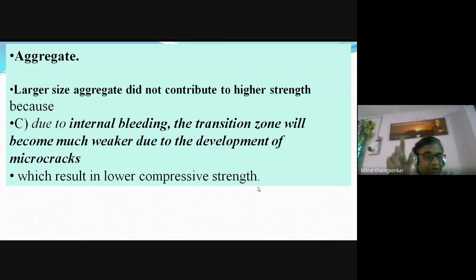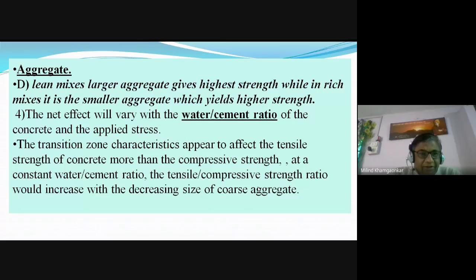Okay, sometimes it is asked in exams why the larger size aggregate gives lesser strength as compared to the smaller size aggregate, or whether the concrete of larger MSA is stronger than the concrete of smaller MSA. You should be able to answer that larger size aggregate does not give higher strength as compared to smaller size aggregate because of these three reasons. Okay, and the last but not the least, which adds to the strength of the concrete due to the larger aggregate, is the lean mixes, means the concrete with lower cement quantity or where the aggregate to cement ratio is larger.